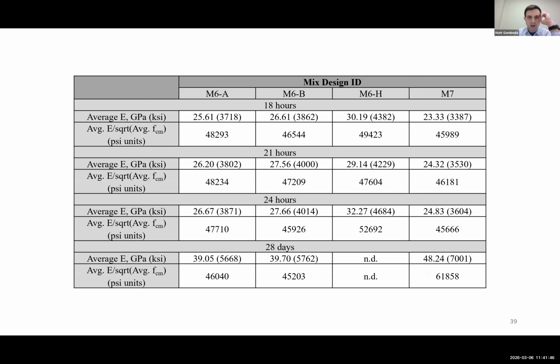And then here's some testing we did on modulus of elasticity, which basically shows that the ACI equation for MOE, which is 57,000, is a little bit unconservative in a lot of these mixes that we did here, likely due to some of the aggregate properties and whatnot. I don't want to alarm anybody here, but one of the suggestions is, if you're going through all this trouble to do the flexural strength testing and compressive strength testing, it's not terribly more difficult to also do the MOE testing, which is going to help get better estimates for things like deflections and stiffness when needed as part of structural analyses.